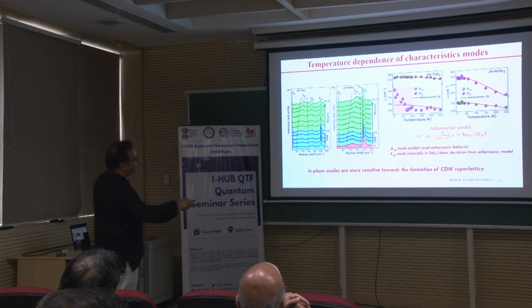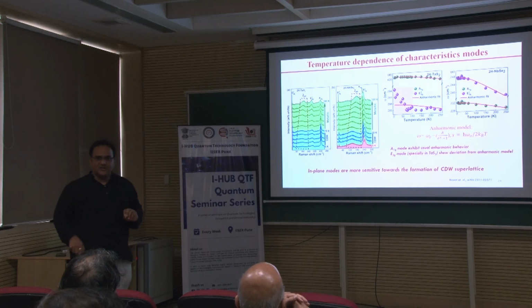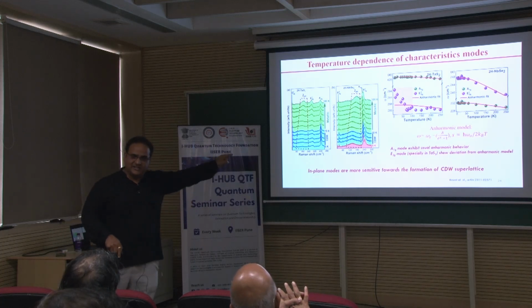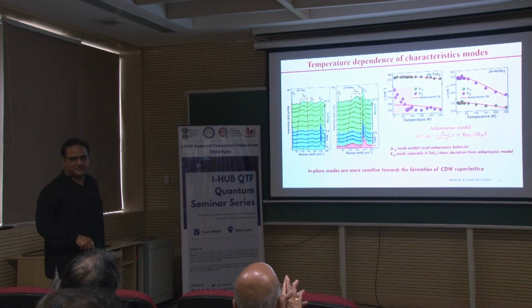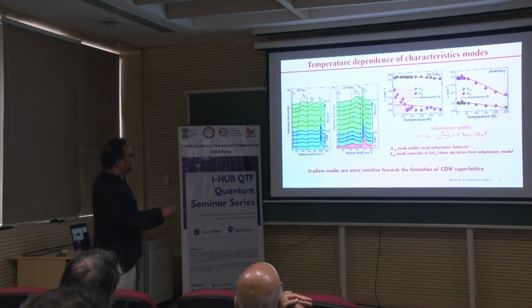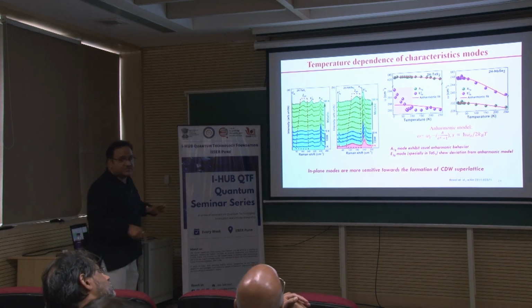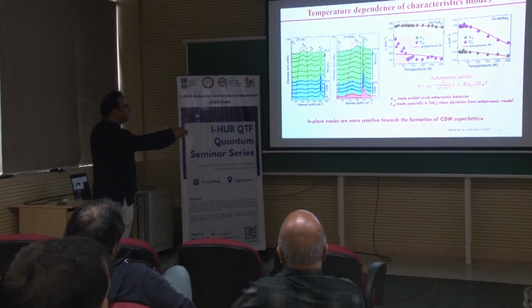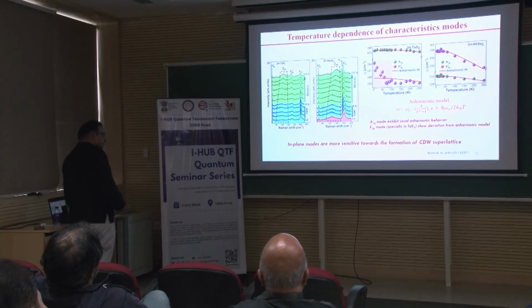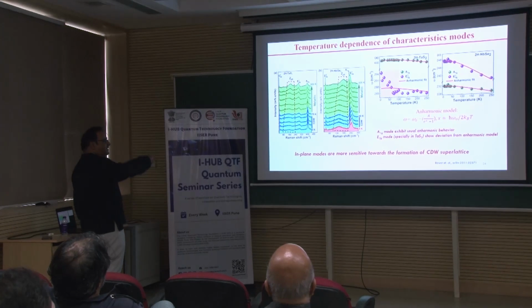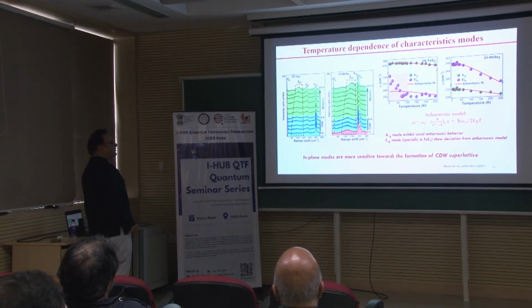But if there is electron phonon interaction, which can drive the anharmonicity or other factors, it is observed at low temperature, which in the case of tantalum sulphide is below 100 Kelvin, you have a deviation. The deviation actually tells you that there is an involvement of electron phonon coupling. So, that is the signature, and for NbSe2 because it is at very low temperature, you have an involvement of the electron phonon coupling. So, the charge density wave in this material is driven by the electron phonon coupling.